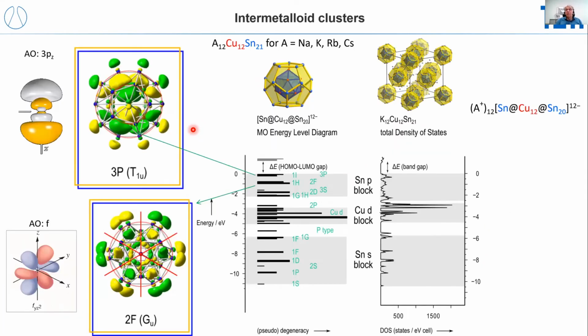then we can do band structure calculation. Here, this is like a density of states. We can do molecular calculation on this hypothetical polyanion here. And we see this is a good match. And actually, this cluster has lots of degenerate orbitals. And if we look at this cluster and look at the overall picture of how the molecular orbitals look, for example, the highest occupied orbital, we get an idea that down there, this is positively charged, up there, this is negatively charged. We get some changes in sign down there.